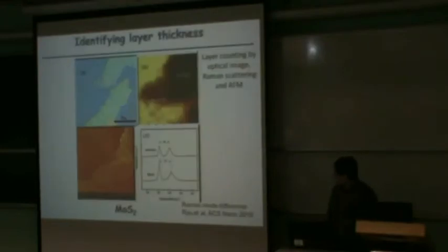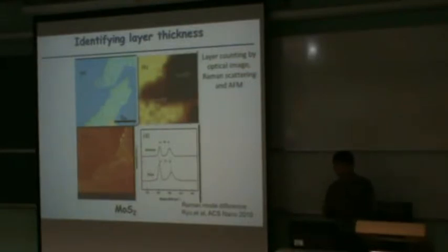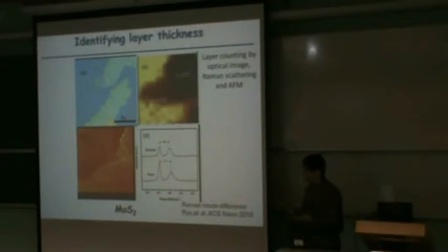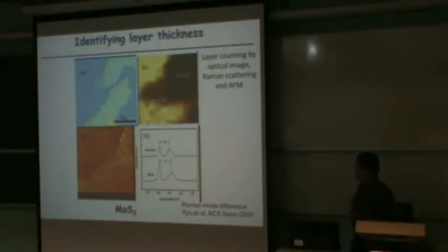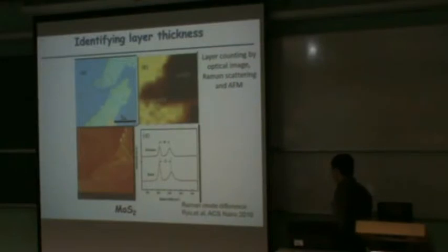Let's start with how to make the monolayer. So far, the popular way is still the Scotch tape method. With the CVD method, we can grow large-scale monolayers, but the quality, as yet, is not that good compared with exfoliated single crystal samples. The method is just like graphene: Scotch tape and that kind of stuff. It's just mechanical cleavage.